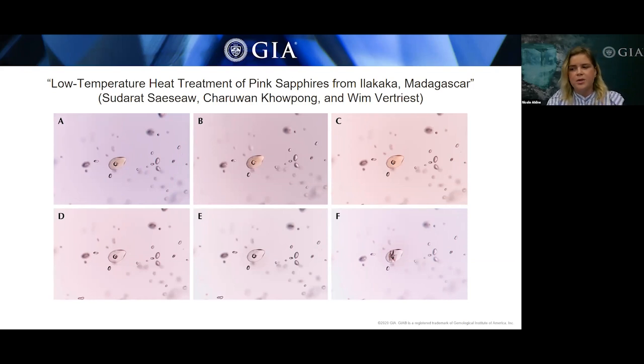So during this low temperature heat treatment, it still remains a challenge since some inclusions such as zircons, needles, and particles are often not affected by low temperature heat treatment. And since we have seen that the presence of the 3232 peak with a 3309 peak in that FTIR spectrum is related to heat treatment, and while this peak is only found in heated stones, the absence of it is still not an indicator that your stone was unheated, but it definitely aids in that call.